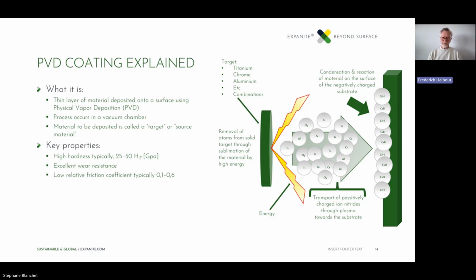Just before that, however, the atoms are ionized with a positive charge, and then it becomes nitrogen ions. So with this positive charge and a negative charge on the part that you want to have coated, the substrate, there will be an attraction of these positively charged ion nitrides on the surface, where they actually will condense like fog on a glass or something like that, but then freeze or become stable and hard. On the surface of the material, the material needs to be clean, of course, and have a good surface finish, but what you do is build up atom by atom. You build up a very, very dense and very, very hard layer of material.